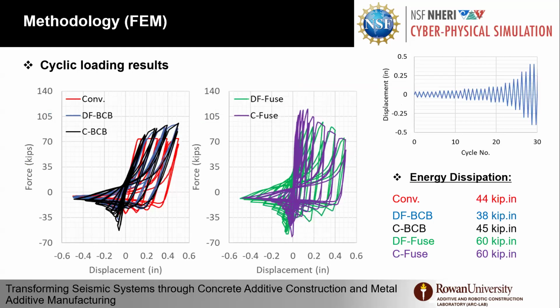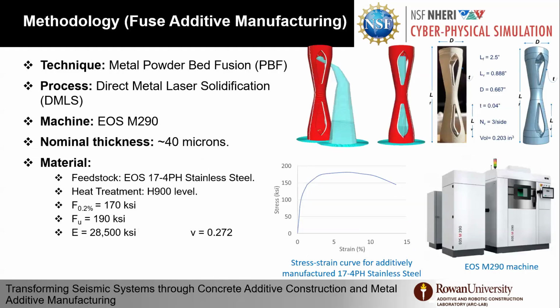Under cyclic loading, you can see on the left side the energy dissipation for the 3 systems: the conventional one, and the hybrid brace with double funnel and cylinder elements, with the energy dissipation numbers on the right side of this slide. And we are able to get a technique that lets us further optimize our fuses to achieve whatever energy dissipation we target. So a lot of the numerical work has to be verified with some testing. So we did test a small design, a scaled version of the fuse.